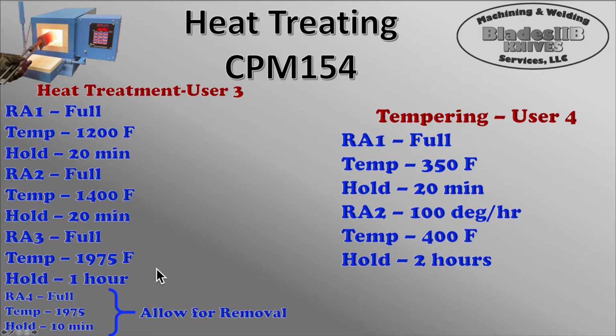If you look online, you can go anywhere from 30 to 60 minutes. I've been going the full hour there, and it seems to be working well for me. And then you can see I've got the same additional program down here for that extra 10 minutes. Same reason as on the 440C, it just gives me time to get a couple knives out of there and make sure it's still trying to hold temperature for that 5 or 10 minutes it takes for me to get the additional blades out of the oven. So that's our cooking temperature, our heat treatment temperatures for the CPM154.